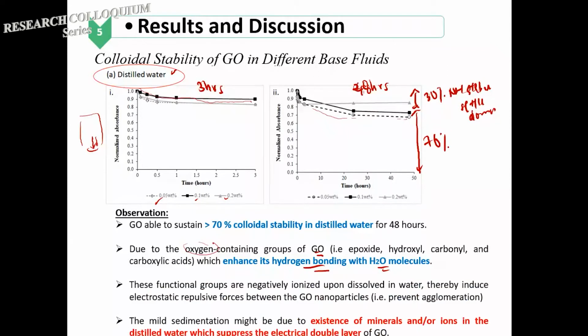However, we still notice that a certain portion of these nanoparticles is not stable and settles down. We believe this mild sedimentation could be due to the existence of minerals or ions, as the distilled water that we use in the lab is not pure water. Definitely inside there are some ions, chlorine, these kinds of ions. These ions can suppress the electrical double layer of the graphene oxide, making it not that stable. So we believe the 30% is due to the chlorine or the ions inside the distilled water itself. This is the first heat transfer fluid that we studied.